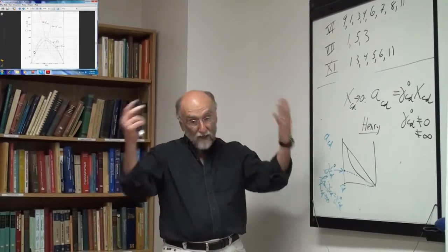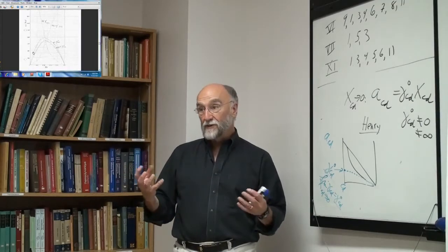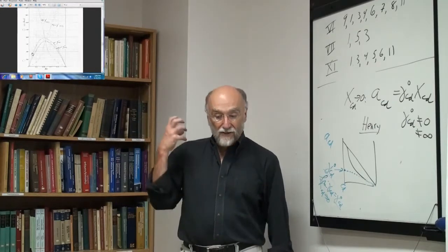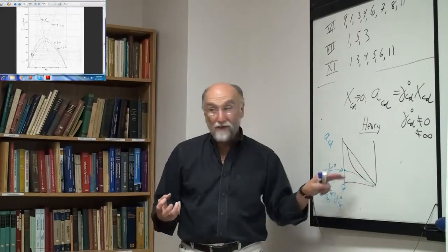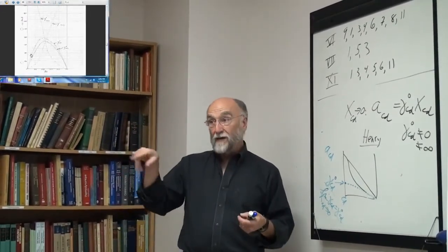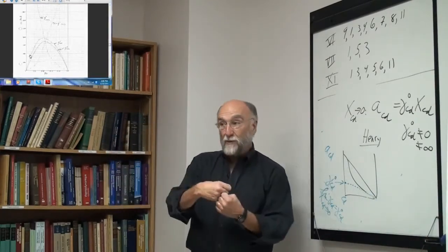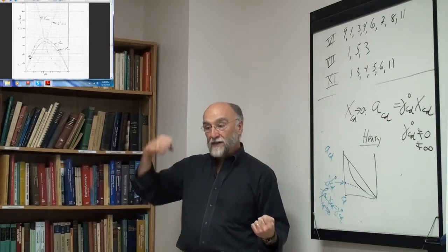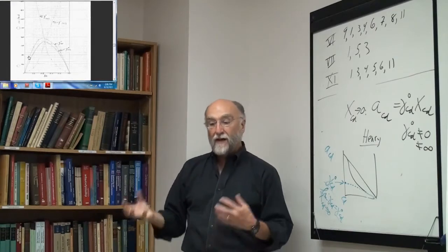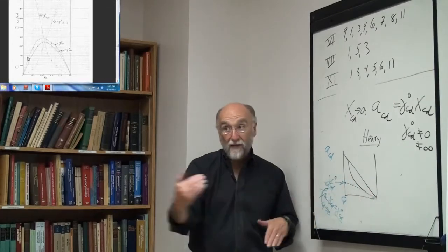Well, it's because if I take a large bath of cadmium and I put in an atom of antimony, it finds itself in a different environment than in pure antimony. It's surrounded by cadmium atoms, so there's an energetic contribution. If I put the second atom of antimony into the cadmium, it's going to find itself again surrounded totally by cadmium, because the probability that those two antimony atoms are going to be next to each other is extremely small. Okay, so as I continue to add antimony to the cadmium, each antimony goes into the same environment as the previous antimony, that is completely surrounded by cadmium. So in that case, you've got more or less a straight line.